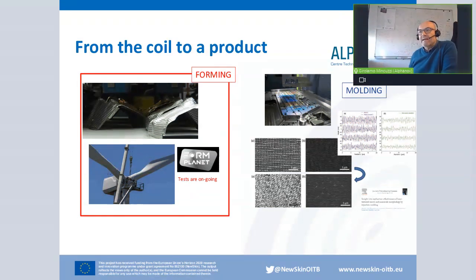What is interesting is that once you have a coil, you can go from the coil to a product by using different technologies. Either you are happy with just the coil because your application needs just a coil without any shape, or you can transfer your structures by molding over, for instance, a polymer. Here you see the test of transferring by molding. On the left is the profile of the structure we generated, and on the right side, the profile of the structure after the molding, which looks quite good.